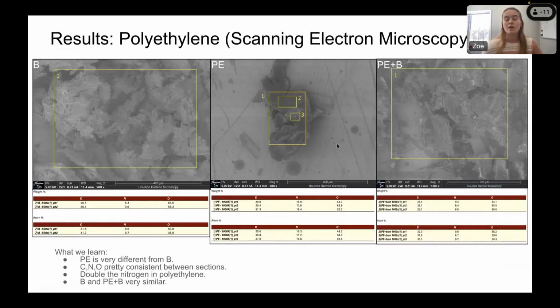In terms of the SEM of the three samples, the bran and the polyethylene bran mixture look very, very similar visibly, and that's reflected in their carbon, nitrogen, and oxygen levels, as you can see right here. However, the polyethylene looks a lot different than the control group. One notable thing is that the nitrogen level is almost double that of the control group. One possible explanation for this is that bacteria have something called a nitrogen metabolism that is used when their other digestion mechanisms don't work. And so that might be a reason why we see the high levels of nitrogen in this sample.